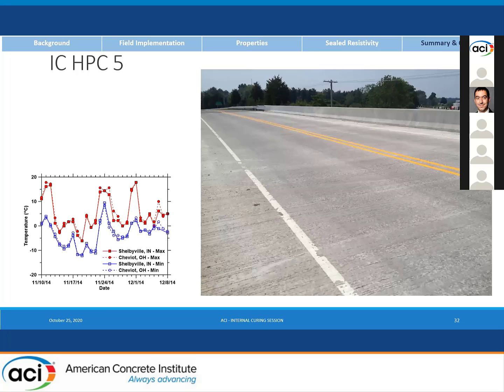And then number 5 was actually interesting because within the first week, we had something like a 30-degree temperature drop because it was cast in November. There are no cracks in that bridge deck. Interestingly, the safety rails were actually not internally cured because they didn't have the support to do that on their own on a different date later on. And so there are a lot of cracks in those rails. And this goes back to what I mentioned earlier about internal curing, providing a significant boost to the thermal cracking component due to the reduction in the coefficient of thermal expansion from internal curing.